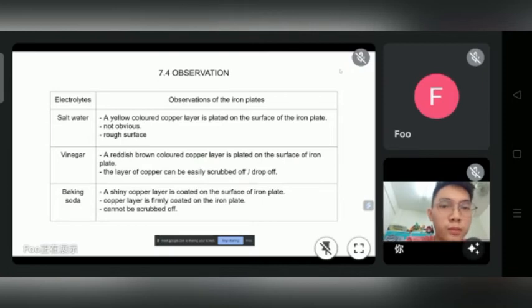So secondly, by using vinegar as electrolyte, a reddish brown color copper layer is plated on the iron plate, and this layer of copper can be easily scrubbed off or drop off. It is unstable. And lastly, by using baking soda as the electrolyte in the electroplating process, a shiny copper layer is coated on the iron plate and is perfectly coated on it and cannot be easily scrubbed off.